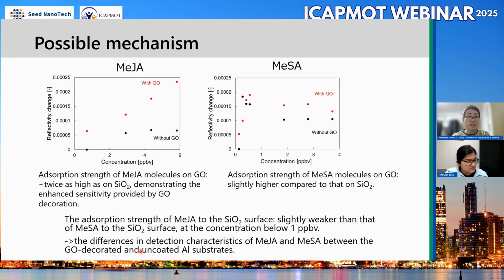So this is the possible mechanism of sensor characteristic for the methyl jasmonate and methyl salicylate. For methyl jasmonate, the adsorption strength of the methyl jasmonate molecule on graphene oxide is twice as high as on SiO2, demonstrating the enhanced sensitivity provided by graphene oxide decoration. On the other hand, for methyl salicylate, the adsorption strength of the methyl salicylate molecule on graphene oxide is slightly higher compared to that on SiO2.